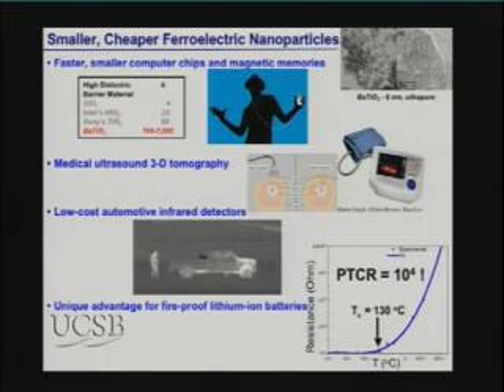And a unique advantage of these materials is their possibility to provide a fireproof coating on the lithium-ion battery electrodes. We found that by doping these with a conductive metal and then sintering the particles to make a fine-grained ceramic, you see a 10,000-fold increase in electrical resistance as a function, just heating above 100 degrees. Very sharp increase in resistance.